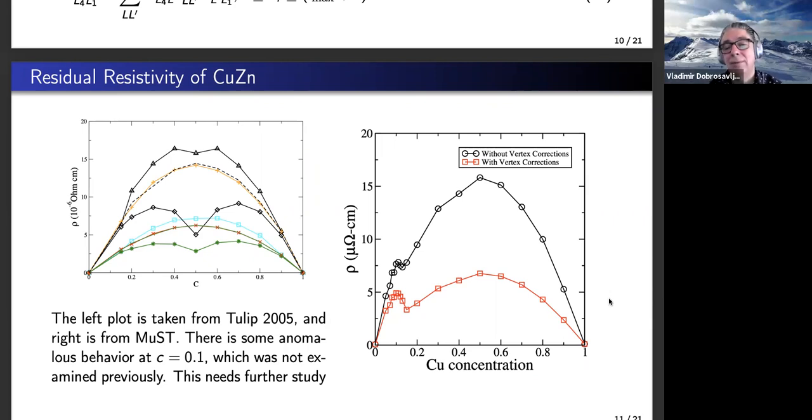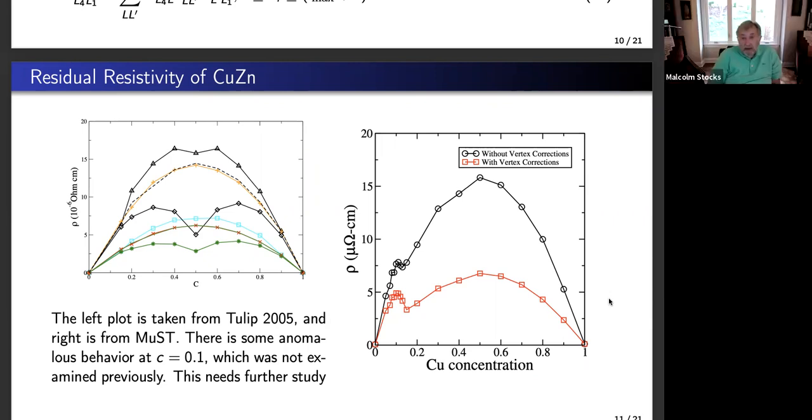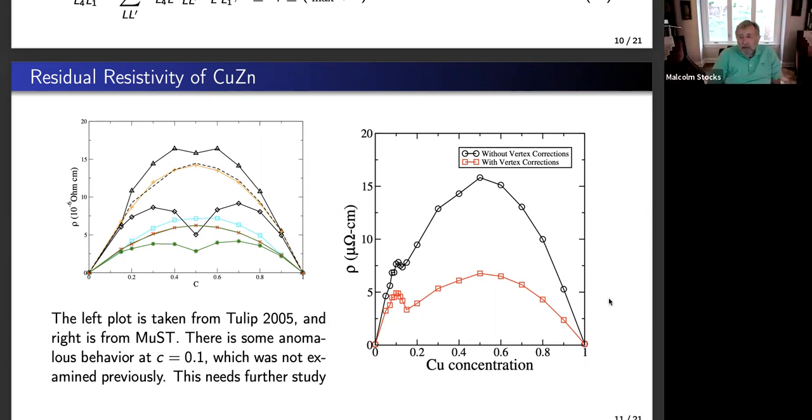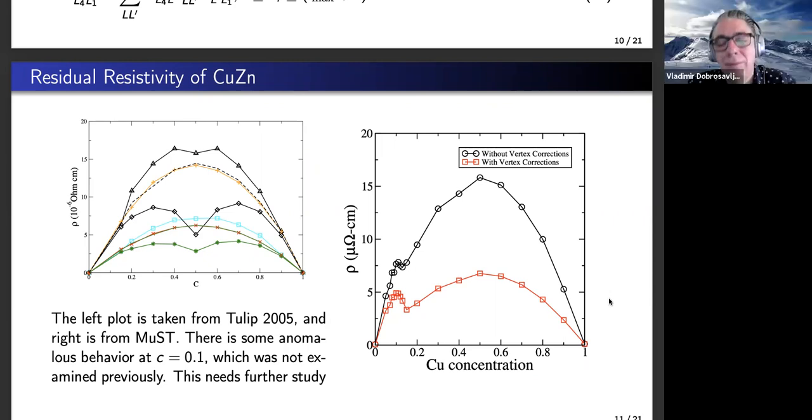Typically the resistivity in these alloys, let's just stick to single phase alloys so that we don't have any ambiguity, goes from basically 0 to typically maybe 100 and odd, 150 or possibly slightly more micro-ohm centimeters. So we've looked at systems where you approach this Mott-Ioffe-Regel limit, right.